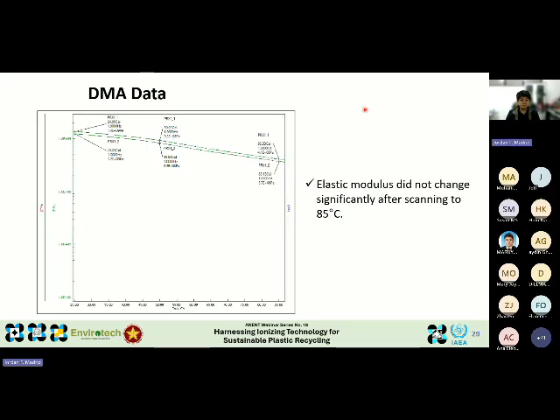One of the important concerns with using these plastic blends for outdoor applications is how they behave under sunlight exposure. In particular, we want to know whether the stiffness of the material changes significantly when subjected to heat. If the sample were to lose stiffness at relatively low temperature, that would limit their use in practical outdoor settings. So our collaborators from ITDI performed a test using a dynamic mechanical analyzer to evaluate the stiffness of the samples at different temperatures, particularly from 25 to more than 85 degrees Celsius.